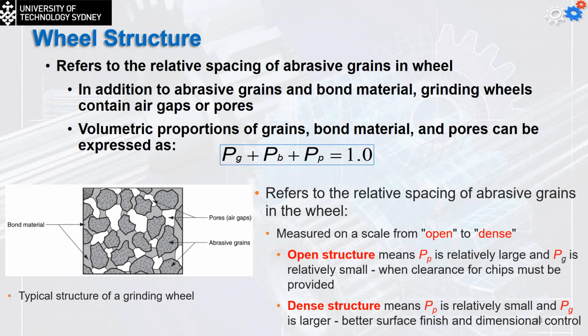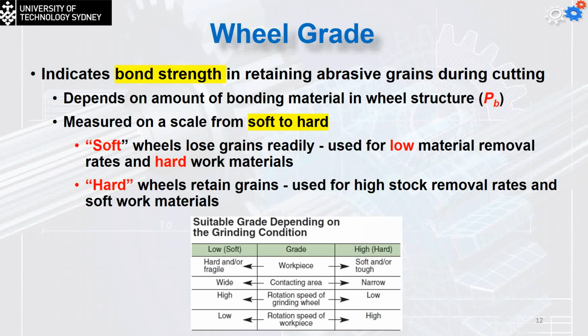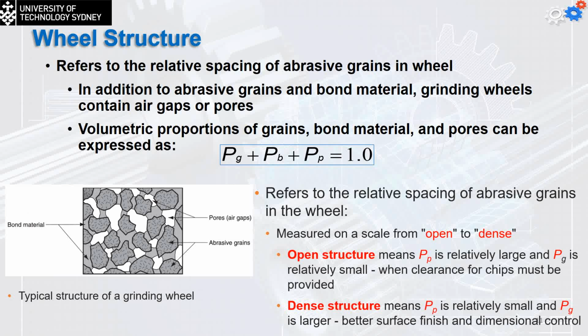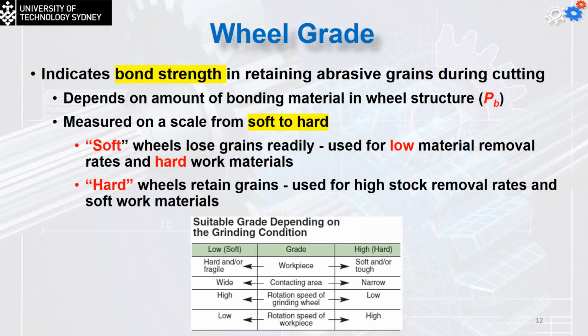The wheel grade, we mentioned that we can have soft or hard. It simply indicates the bond strength in retaining the abrasive grain during the cutting, and that depends on the amount of the bonding materials in the wheel structure. What is the percentage of the PB in the volume of the wheel structure? It's measured from scale soft to hard. The soft wheels are going to lose the grain readily, used for low material removal rates and hard work material. The hard wheels retain grains, used for the high stock removal rate and soft work material.